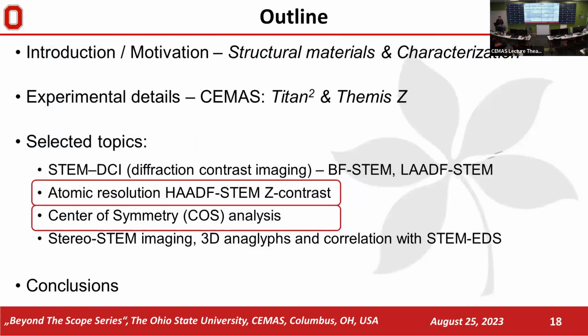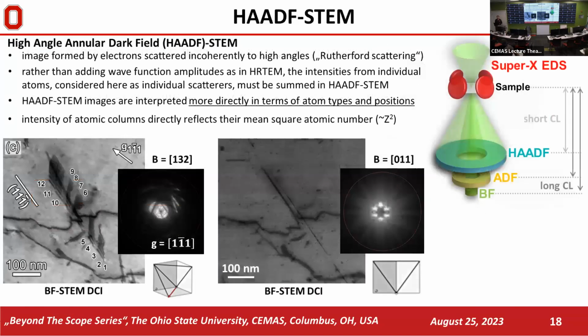So now I'll be talking about atomic resolution HAADF STEM in combination with COS. When we are using high-angle dark field STEM, we switch the camera length, and our image is formed by electrons scattered to high angles. And there's a huge benefit, especially in atomic resolution study of these defects, because in HAADF STEM the images are interpreted directly in terms of atom types and positions. Basically, the closer your convergent probe comes to the atomic column position, the more scattering you get, so the intensity and signal in contrast increase. So where the bright spot, the high intensity contrast is, that's where the atomic column position is.